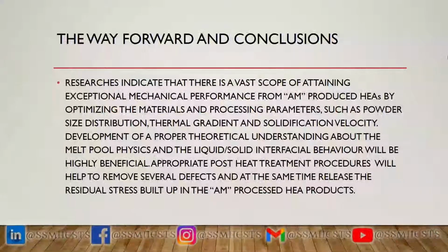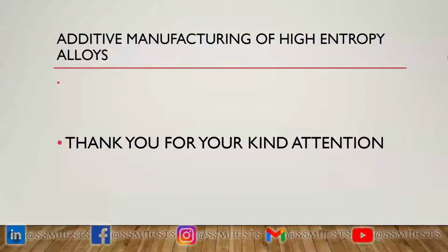So what is the way forward? Now, researchers indicate that there's a vast scope of attaining exceptional mechanical performance from additive manufactured product, produced HEAs, by optimizing the materials and processing parameters. And what are these? The powder size distribution, thermal gradient, and solidification velocity. Now, some theoretical understanding is still lacking about the melt-pool physics and the liquid-solid interfacial behavior. So these are the areas where a lot of work should be done. And the other thing is, there will be some highly beneficial post-manufacturing heat treatment, which should also be taken care of.